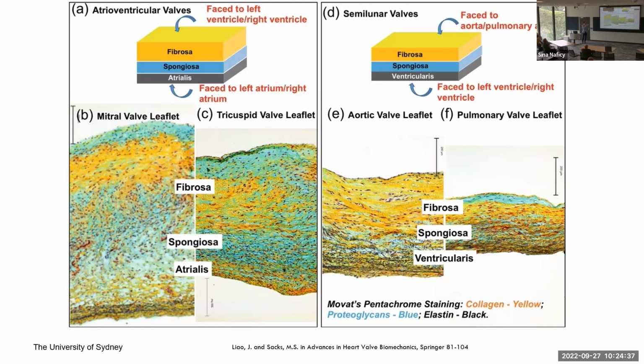If you look at the aortic leaflet or pulmonary leaflet, we would see that the layer which is facing the artery is rich in collagen. The layer at the opposite side is rich in elastin. The layer in the middle is actually a swollen network, basically like a hydrogel.